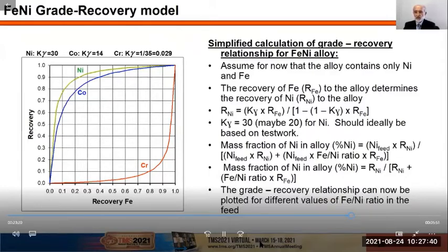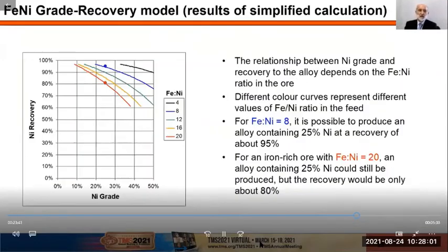We can simplify a fairly complex relationship to ultimately get our mass fraction of nickel in the alloy as a function of the recovery of nickel, the recovery of iron, and the iron to nickel ratio. So this will allow us to plot the grade recovery relationship for different values of the iron-nickel ratio in the feed materials. And this set of curves is now shown in the graph on the left-hand side.